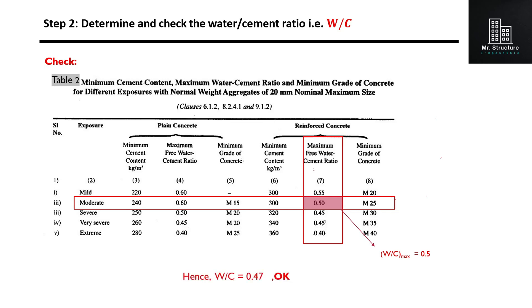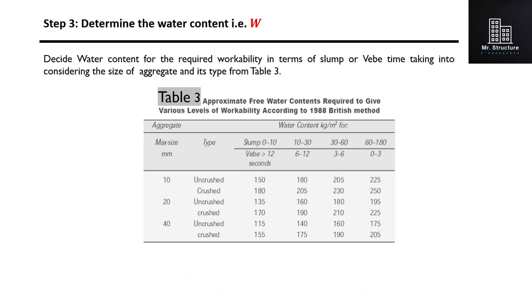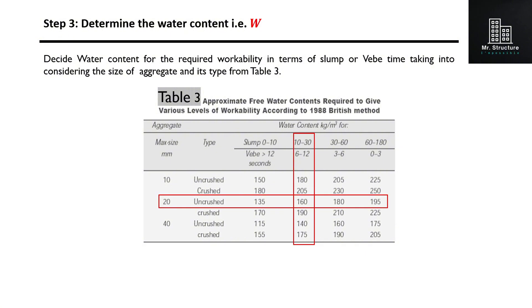In other words, we choose the lower of the two water-cement ratios, since lower the water-cement ratio, better the strength. In step 3, we determine the water content W, that is the weight of water in 1 meter cube of concrete. For maximum aggregate size 20 mm, aggregate type uncrushed, and slump value 10 to 30 mm, we get the water content to be 160 kg per meter cube.